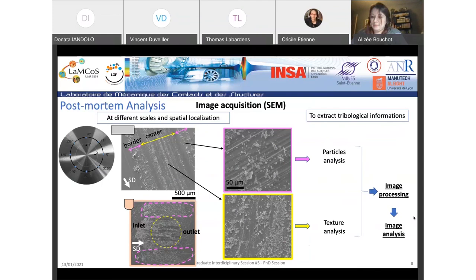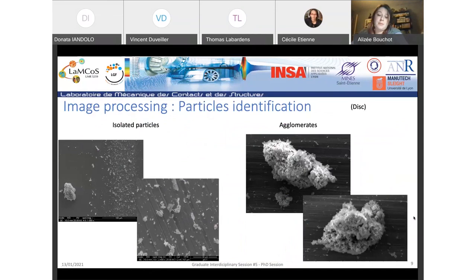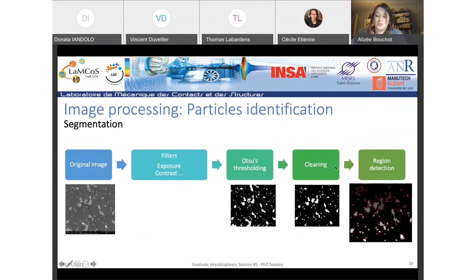As specified above, third body particles may present in different structures. We have isolated particles and agglomerates. To obtain geometric and morphological characteristics, it's necessary to segment the images. For this, we use a code developed in Python. This will make it possible to perform several operations on the image. If necessary, of course, you could apply a filter, modify exposure, contrast, or another image processing operation. And after, the image undergoes thresholding with the Otsu algorithm.